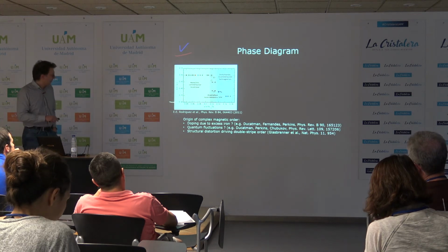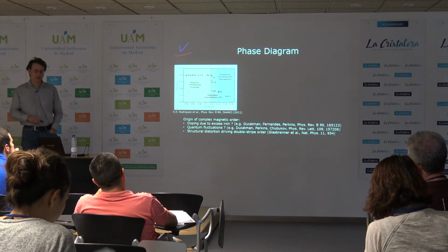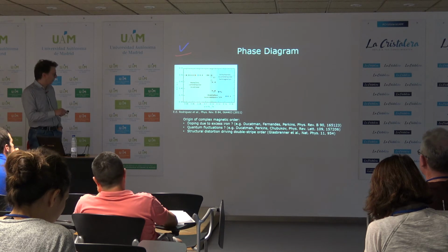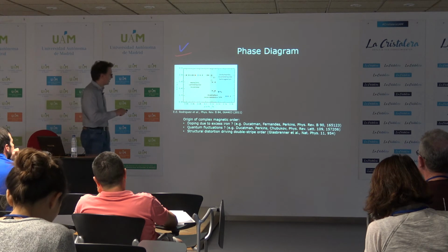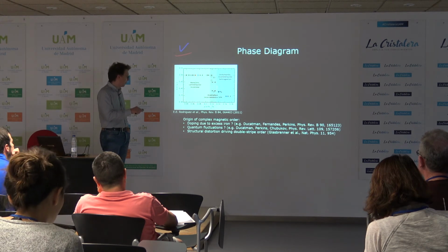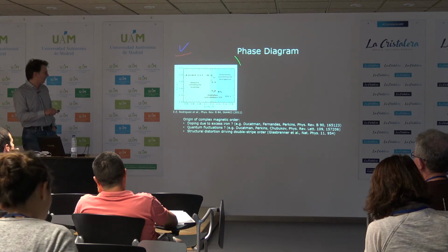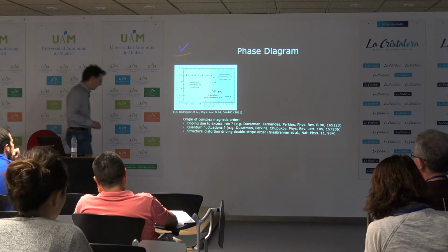And as a function of this excess iron concentration, they have a relatively complex phase diagram where you start out for low excess iron doping with this bicollinear magnetic order I've just shown you. But then as you increase the excess iron doping, the material goes through an incommensurate spin density wave phase and then ends up in an orthorhombic incommensurate helimagnetic phase, according to neutron scattering.